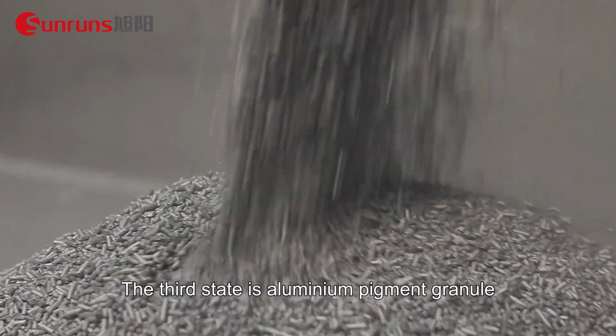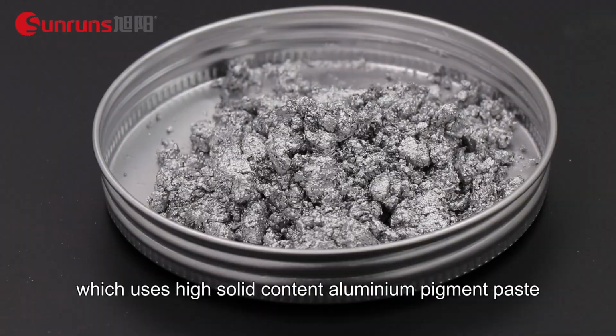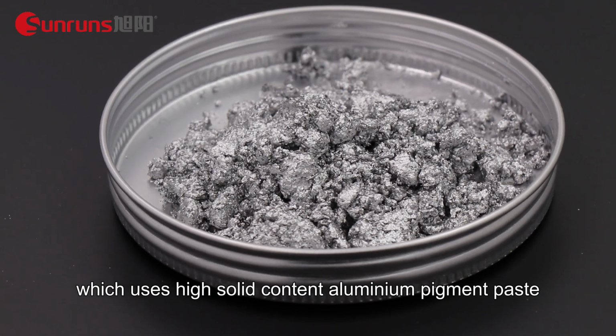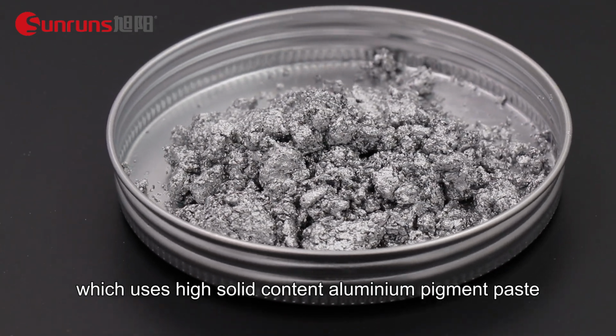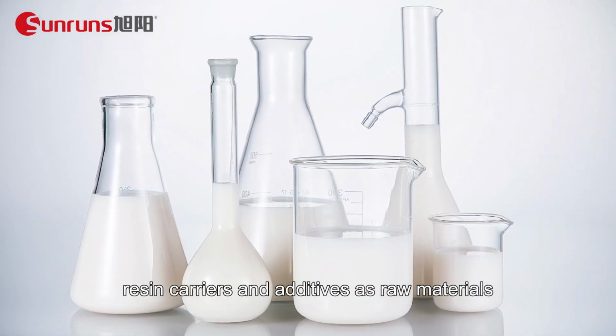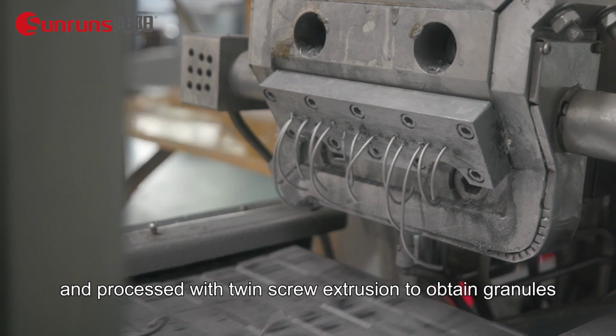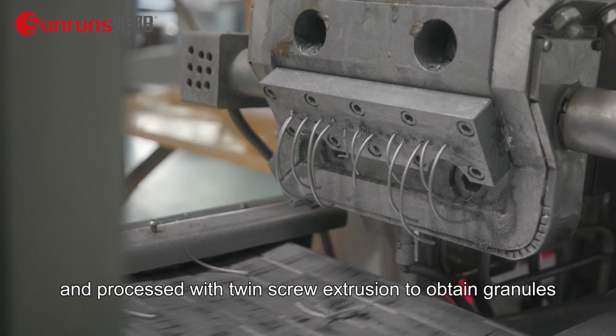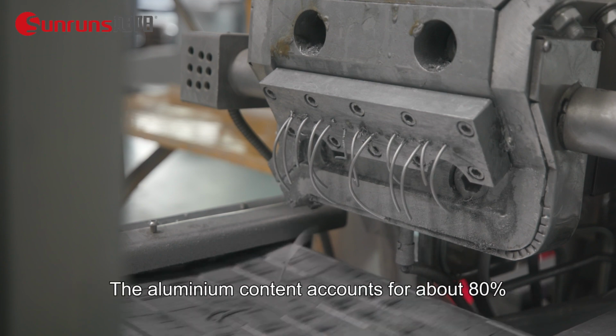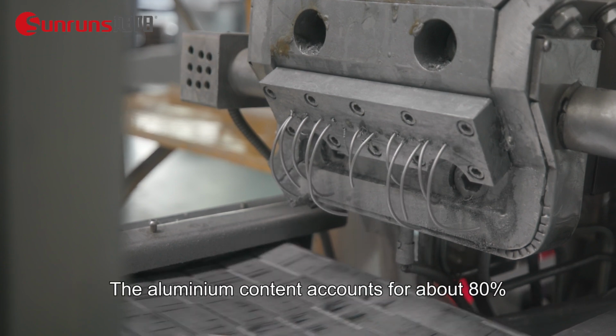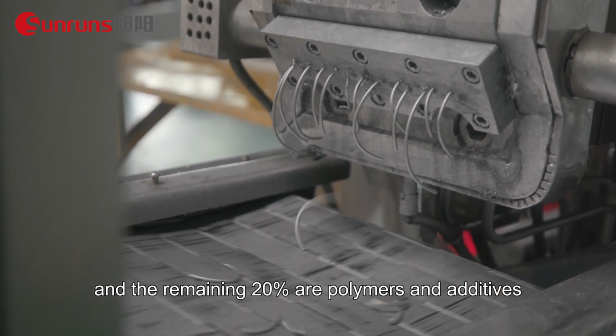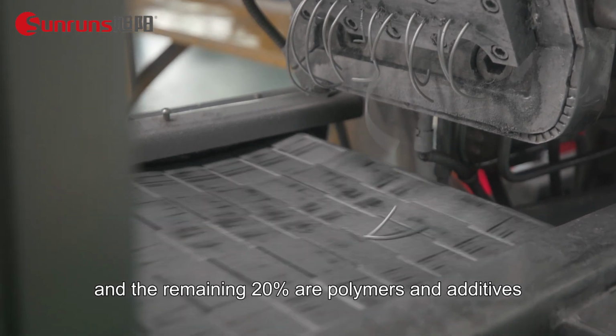The third state is aluminum pigment granule, which uses high solid content aluminum pigment paste, resin carriers, and additives as raw materials, and is processed with twin screw extrusion to obtain granules. The aluminum content accounts for about 80%, and the remaining 20% are polymers and additives.